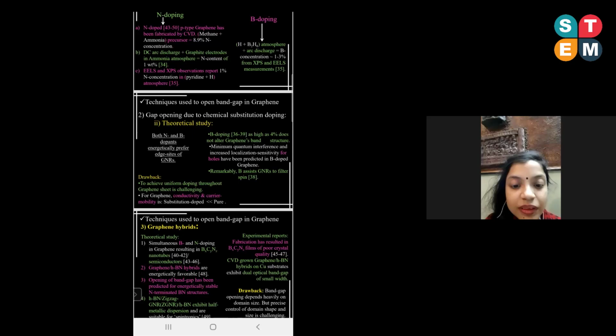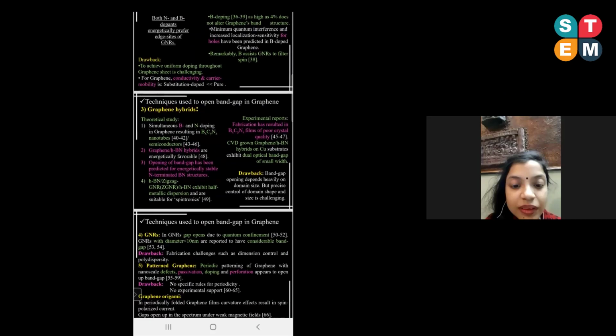But band gap opening is a bit challenging with these dopant ideas. To achieve uniform doping throughout the graphene sheet is challenging, and as we have already pointed out, near the H sites the band structure varies, so it faces difficulties. And substitution doped graphene has much lesser conductivity and carrier mobility as compared to pure graphene, which basically defeats the entire purpose of graphene electronics.